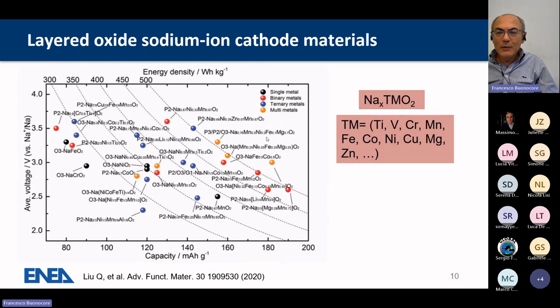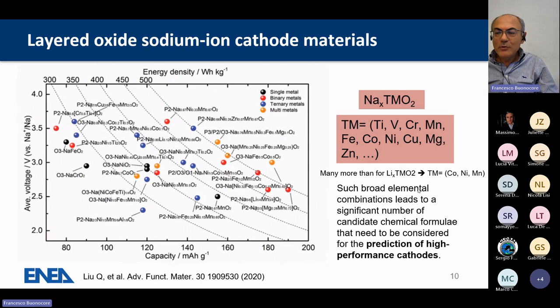The region of this plot where we like to start is the one with high average voltage and high capacity. So this is the region we like to stay in. To reach this region, we need ternary and multi-metal oxides. This is just a selection of possibilities, but we like to screen all the possible materials. This is impossible to do experimentally, but computationally the story can be different. So we need to explore a broad range of elements or combinations of elements. We have different candidate compositions, and we need to predict the optimal crystal structure for high-performance cathodes. This is the purpose of this research.